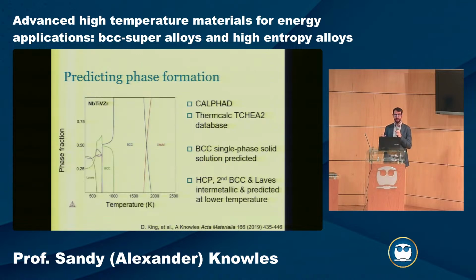So we can attempt to use CALPHAD. CALPHAD is particularly used in this software program run by Thermo-Calc. There are FactSage and other providers of this software. We can use that, and it will tell us the potential phases that might form with temperature for these specific compositions. In this case, it's probably only 20, 30 seconds, maybe a minute per composition. But if you want to do 100,000, then it's not really feasible on that large scale. Also, there is the interpretation of the data.